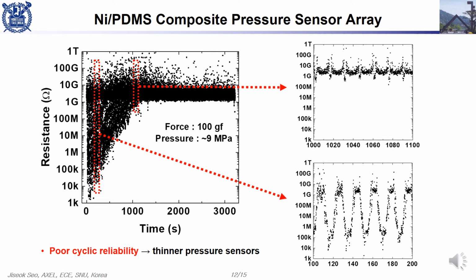This phenomenon may be due to rearrangement of nickel particles in polymer matrix, and I have a result of improved cyclic characteristics with thinner sensor sheet. So I'm in the process of fabricating new silicon mold with shallower hole arrays to make a sensor sheet thinner than this.